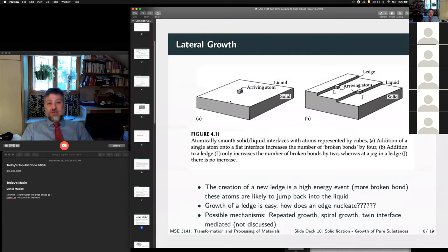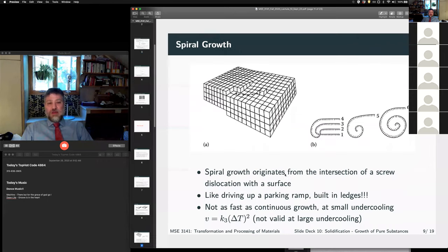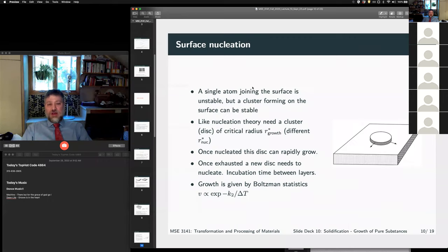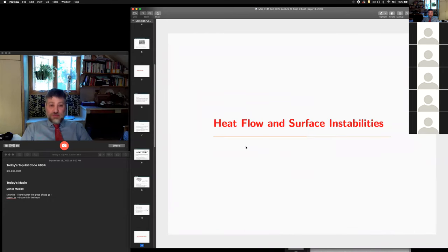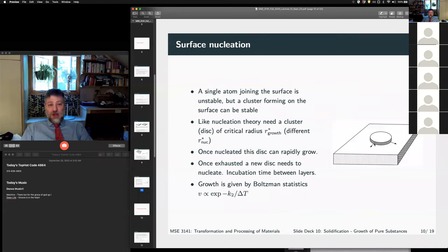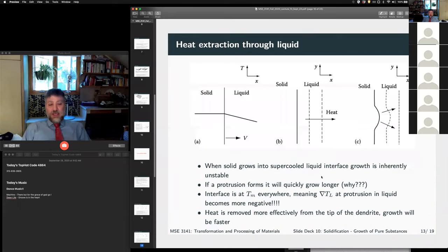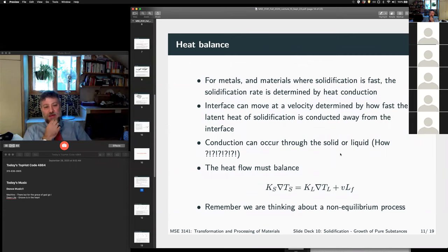However, if we have a smooth interface, it's very difficult for a new atom to come, and we either have to take advantage of a spiral growth like this or continual nucleation at the surface. Then I wanted to differentiate between a rough interface and a planar interface, right? The rough or diffuse interface means that at the atomistic level it's crinkly, right? But planar is more of a macroscopic description, right? Is the growth front moving as a plane, or is it moving as some kind of curved surface growing out? And so we want to express some conditions as to when the two are going to happen.